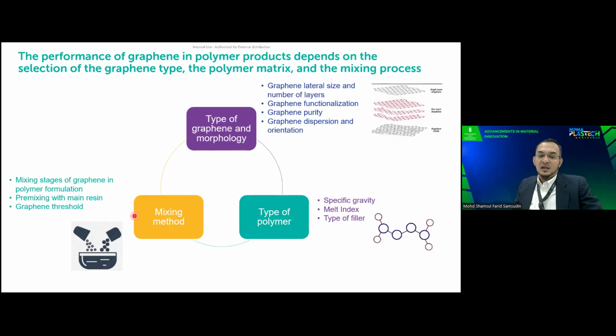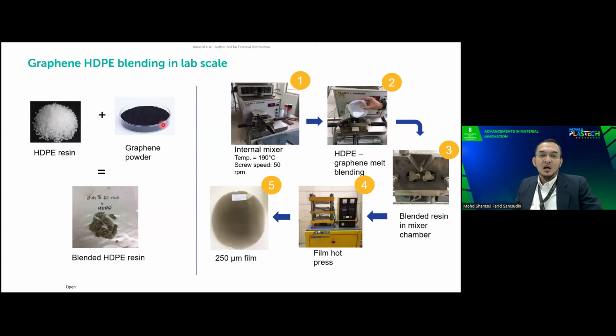And other than that, in terms of the mixing method, how well we mix the graphene particle in the polymer. For example, if we want to mix this graphene particle in the thermoplastic, we need to understand whether we require a kind of pre-mixing to get the graphene dispersed first in the powder form of the polymer or in the pellet form, and after that we will add into the extruder for the melt blending process. And this is an example of how we carry out the study.